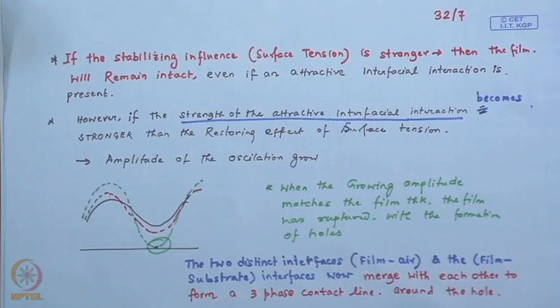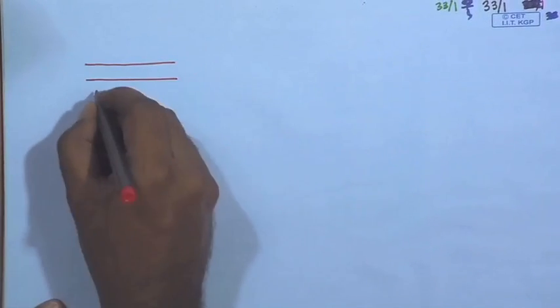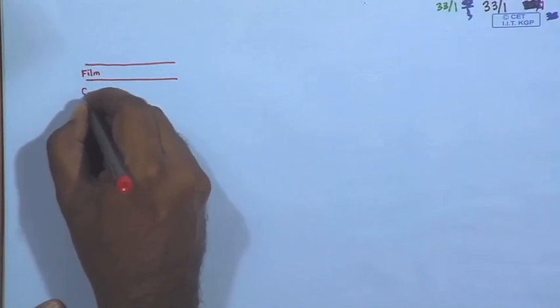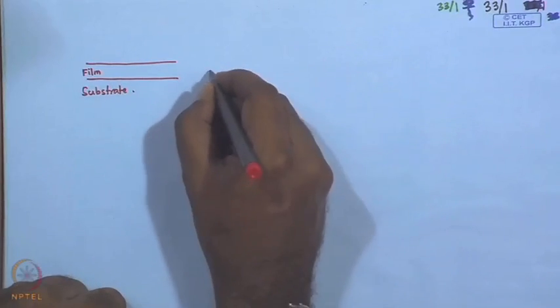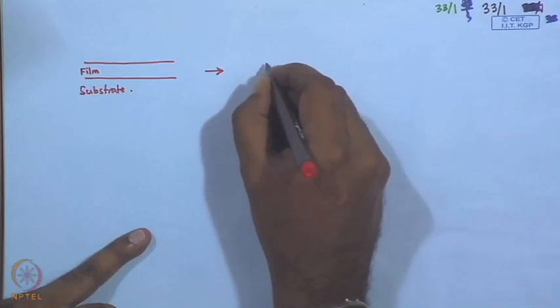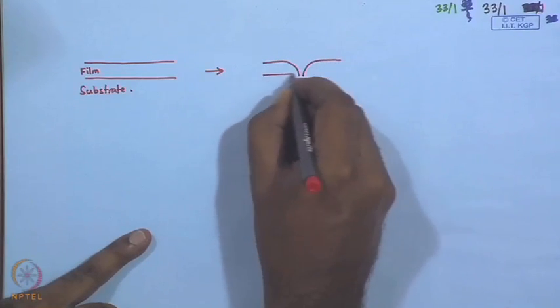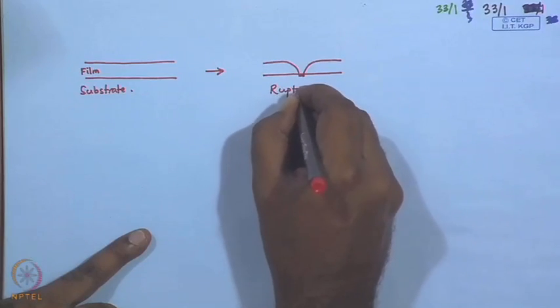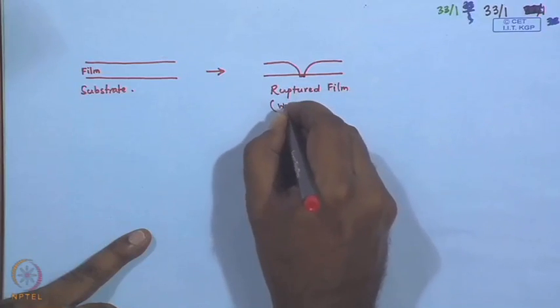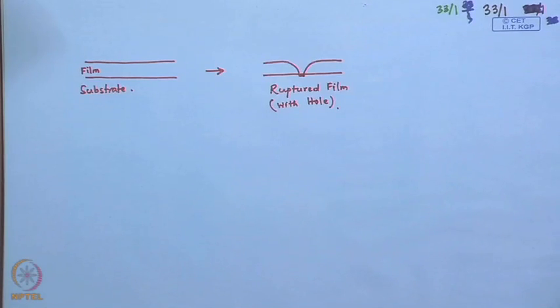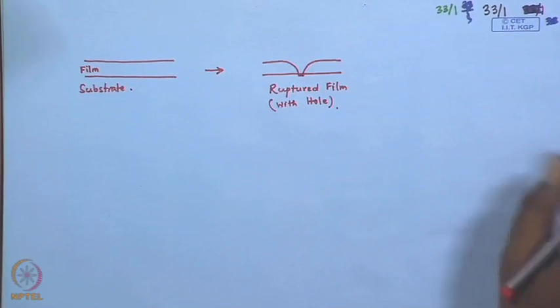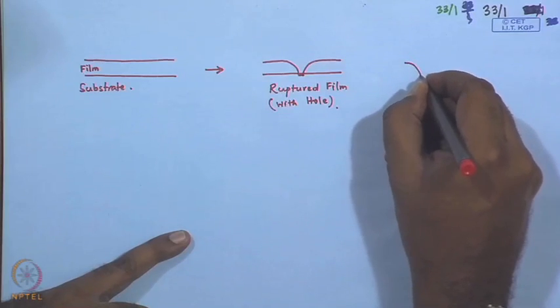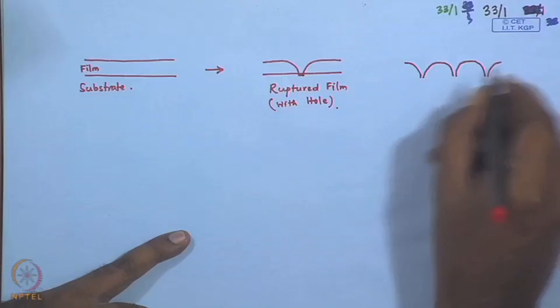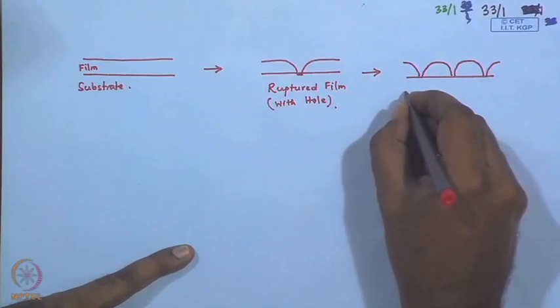Now, there is some additional subsequent dynamics. So, the scenario is like this. All you have done is that you have taken a film on a substrate, and simply based on the strength of the attractive interfacial interaction, this film has ruptured, forming a hole. Now, if the surface is defect free, there is no preferential spot where a hole should nucleate. There is no reason to assume that only one hole will form, and what eventually happens is that several holes form like this, and the dynamics or the evolution